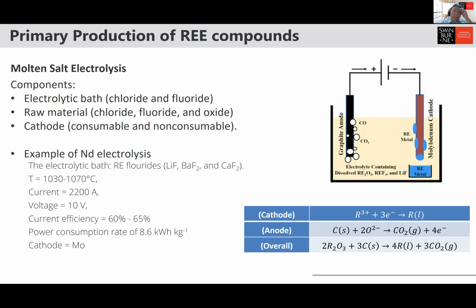So typically, for example, for the Nd neodymium electrolysis, we use lithium fluoride, barium fluoride, and calcium fluoride for the bath. The temperature is usually about 1030 to 1070 degrees Celsius. We use current of about 2200 ampere, voltage of 10. We can use cathode made of molybdenum, and the power consumption rate is about 8.6 kilowatt hour per kilogram. Right. So that's the molten salt electrolysis process to make neodymium. So the basis of the voltage is, of course, the decomposition voltage of the particular element itself. Yeah.